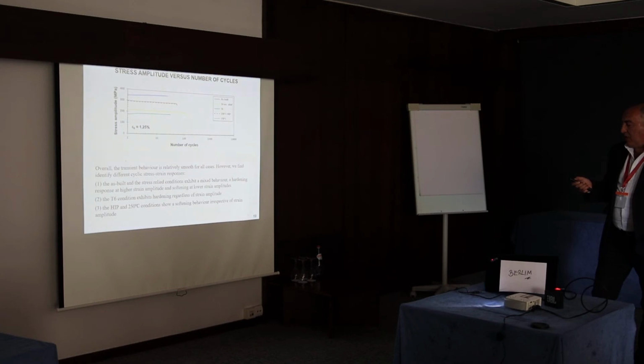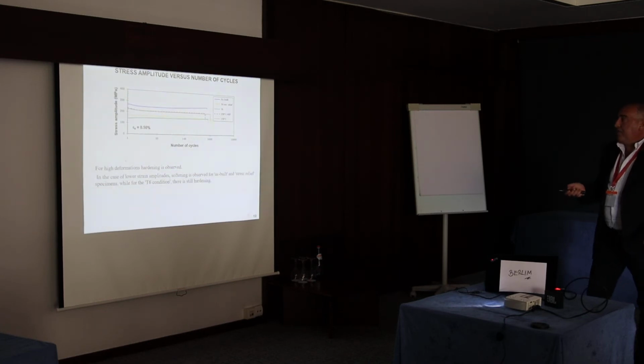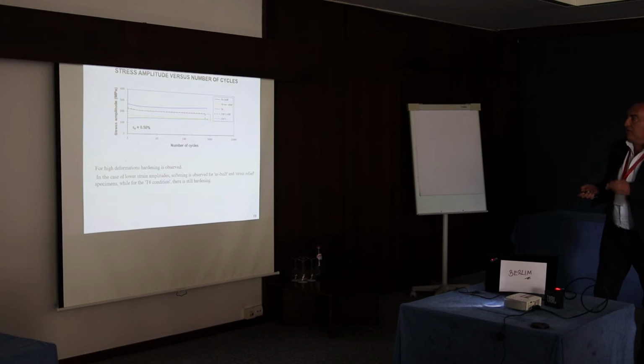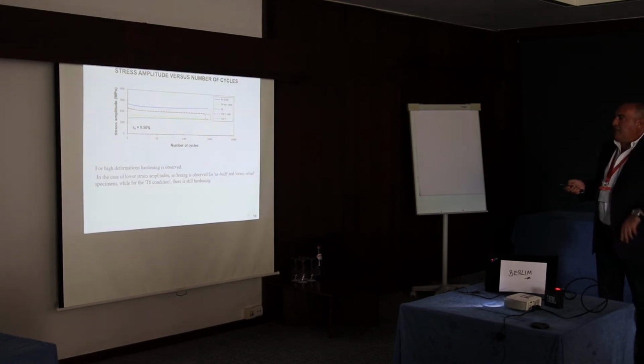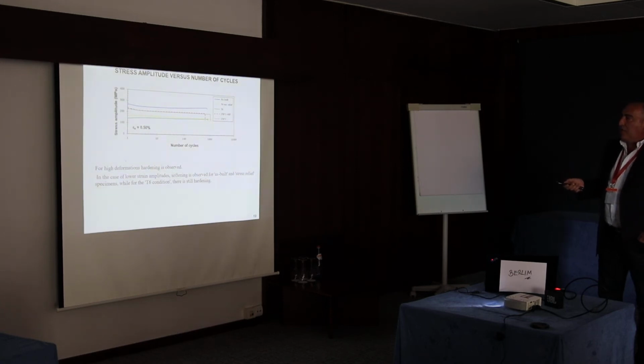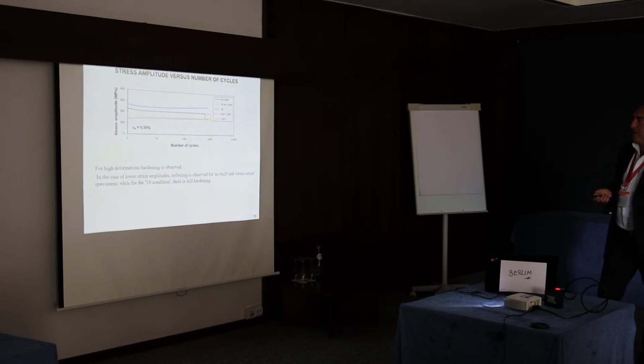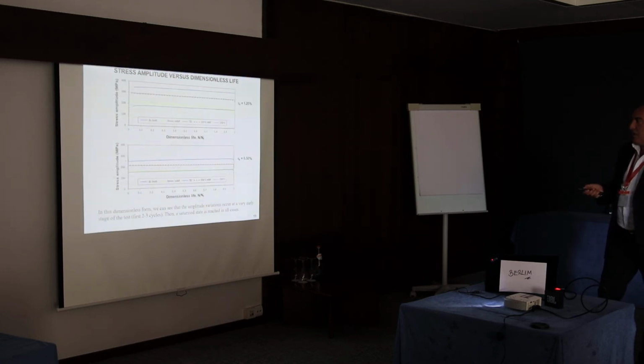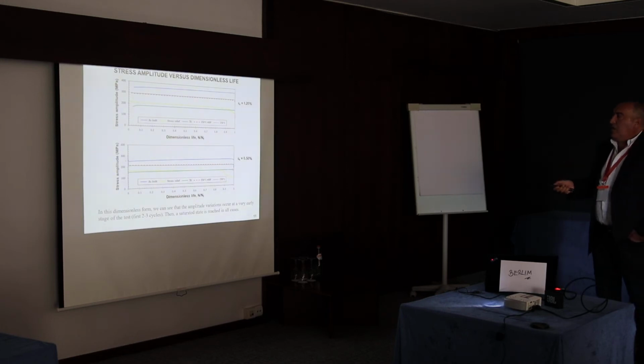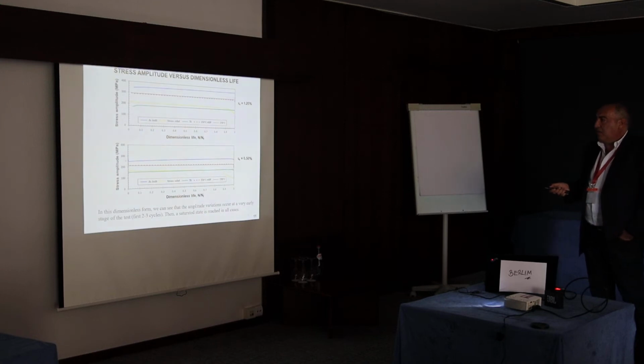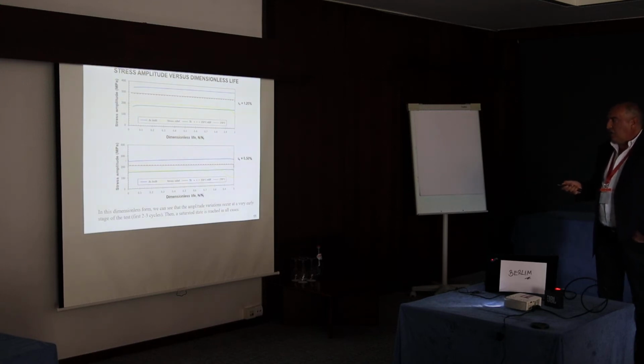When we compare the normalized, this is for the lower stress amplitude, this is for a strain amplitude of 0.5. We can see easily that for high deformations hardening is observed, and for the lower strain amplitude softening is observed for as-built and stress relief. When we put it in the form of dimensionless life, we can see that the amplitude variations occur at a very early stage, only for the first 2-3 cycles, then a saturated state is reached in all cases.